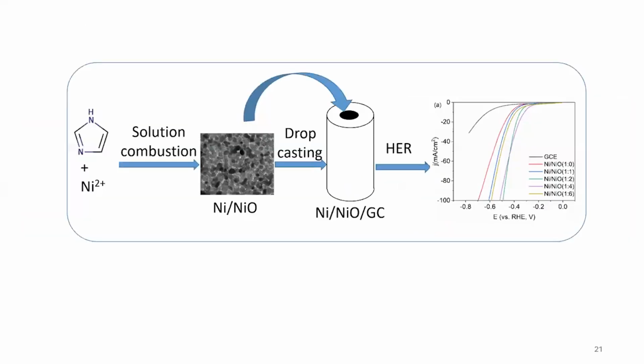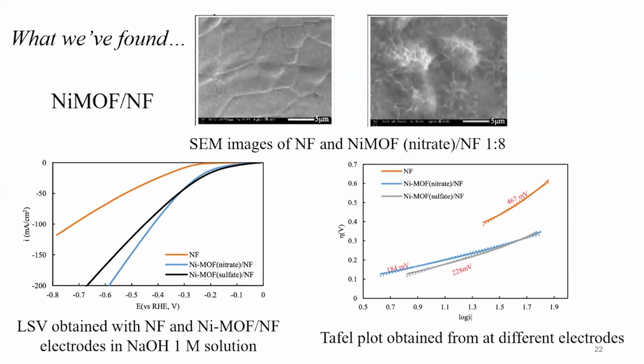And the second material is also from nickel-based MOF, but then we anneal that to form a nickel and nickel oxide composite, also for electrochemical water splitting. So what we found is that the use of different nickel salts will give different performance. In this research, the nickel MOF synthesized from nitrate salts gives the best result. Here we examine the Tafel plot to estimate the performance of hydrogen evolution.